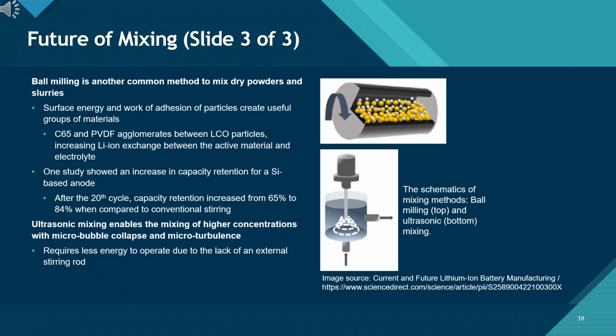Future of mixing, Slide 3 of 3. This slide introduces two emerging mixing techniques, ball milling and ultrasonic mixing, that help improve slurry uniformity and electrochemical performance. Ball milling is widely used for both dry powders and slurries. During milling, particles form beneficial agglomerates due to surface energy interactions.